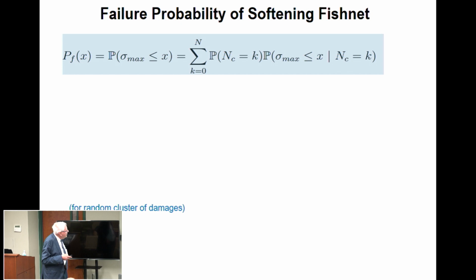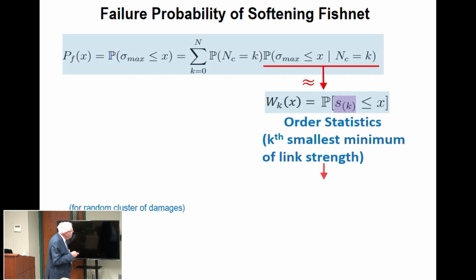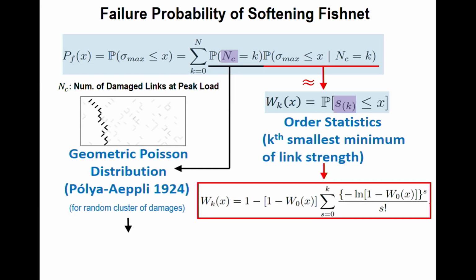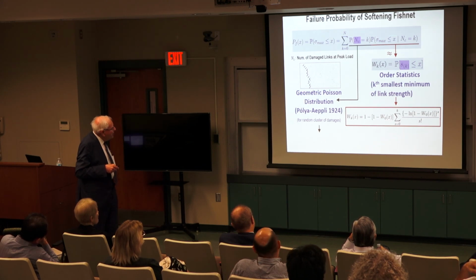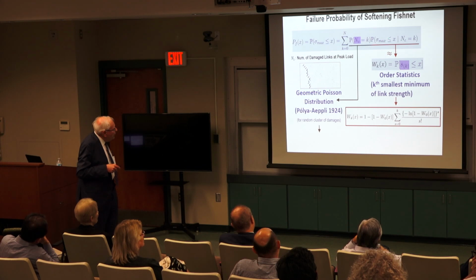So a series of jumps means that we don't get failure from one jump. Right? We need a number of them. We may need 20 jumps down, and then we don't need the minimum strength. We need the K-th minimum, where K can be the third minimum, or fifth minimum, or tenth minimum. Now this is the subject of a well-known theory, order statistics. All right, so the probability of failure is then the probability of how many jumps you have going down, which is a random number itself, and the probability given that number of jumps, K, conditional, K-th minimum, that sigma is given, then the arguments, then the load, K.